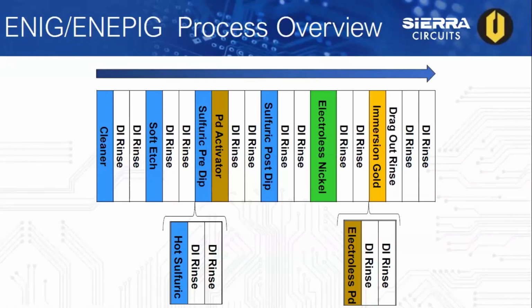The cascade DI water rinses are used throughout the process to ensure that we basically eliminate dragged-in chemistry for the purpose of avoiding cross-contamination of the other chemicals. Now an etch bath is then used. This etch bath will help smoothen the copper, and this will remove approximately about 1 to 1.5 microns of copper thickness.